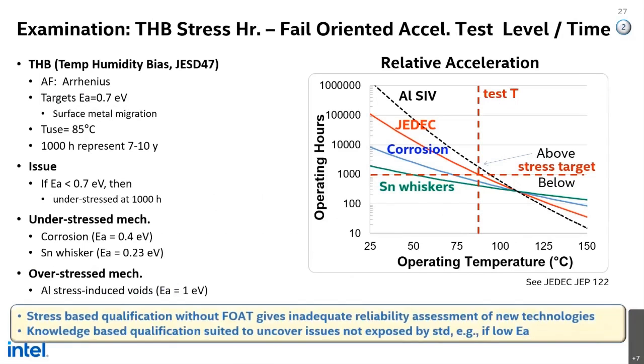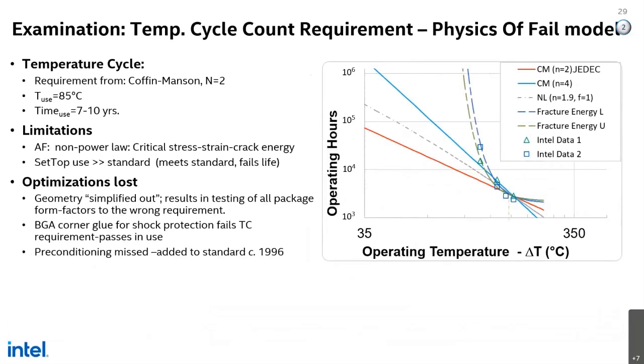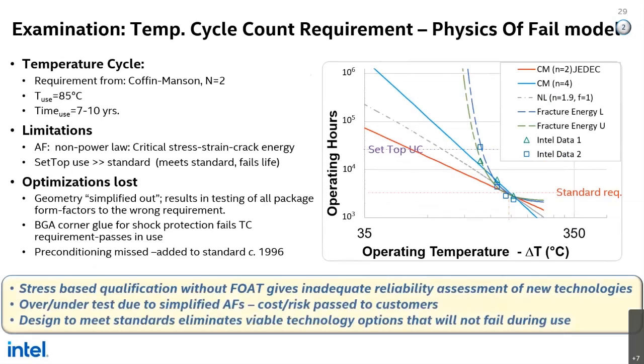And the same thing applies here for the temp cycle. If you take a model, Coffin-Manson, for instance, that has certain assumptions in it and certain simplifications, and if you follow that model, you might have a technology that fails, but it passes in the use case. And it passes maybe in a more rigorous environment, a set-top environment, but it would fail in the stress-based qual test. So you lose optimization, you lose markets.